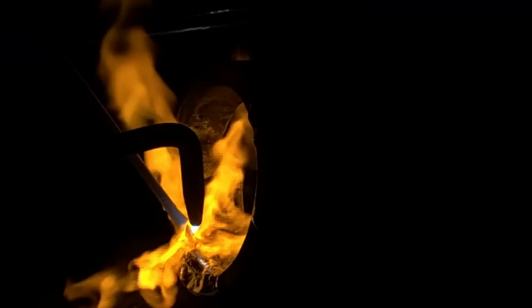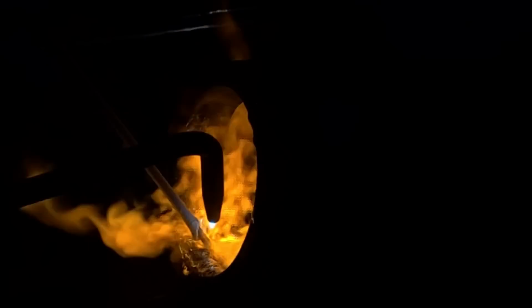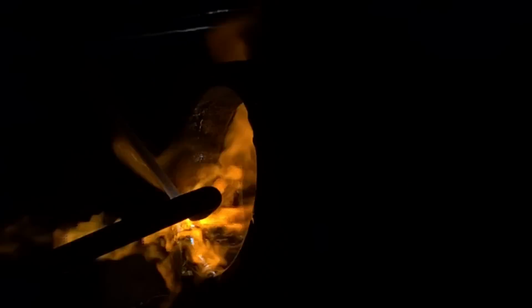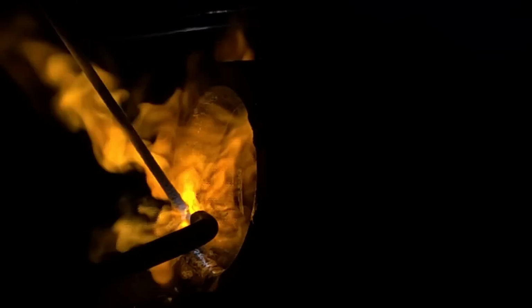I don't know what kind of crud is there in the iron. There's a little bit of crud there. It was hot enough, but it wasn't wanting to stick, so I ran it on over to the edge. Might have been too much flux floating around in there, because we got a pretty good puddle of flux built up, but I think it's probably more contamination at the bevel.